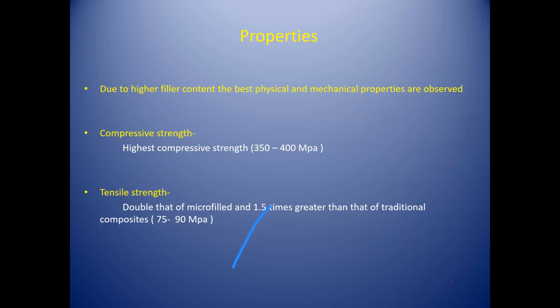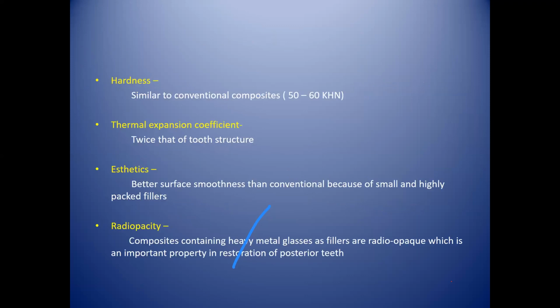Its properties: due to high filler content, the best physical and mechanical properties are observed. Compressive strength is around 350 to 400 MPa. Tensile strength is around 75 to 90 MPa. Its hardness ranges from 50 to 60 KHN. Thermal expansion coefficient is twice that of tooth structure.